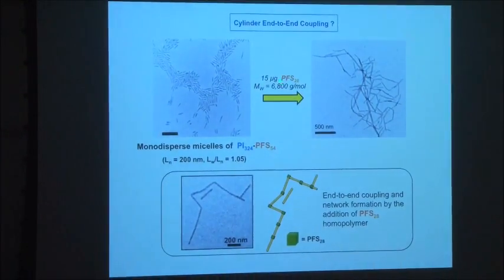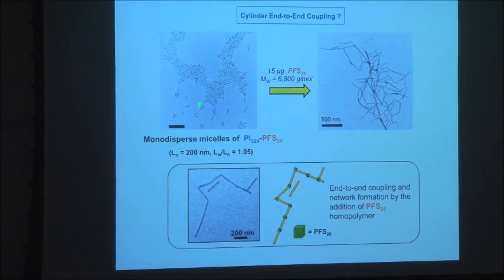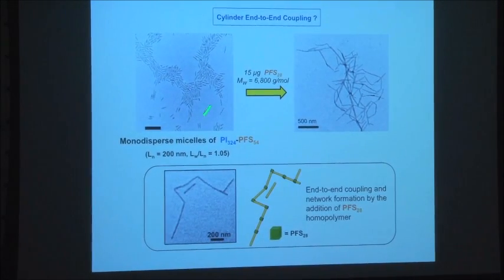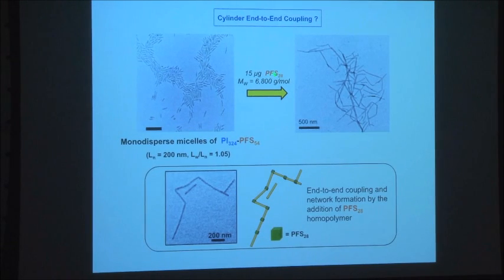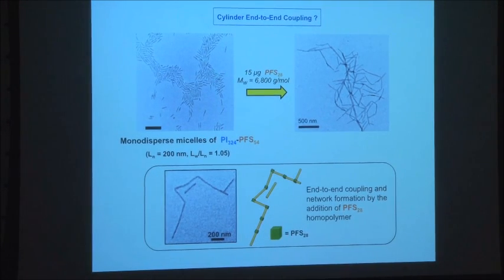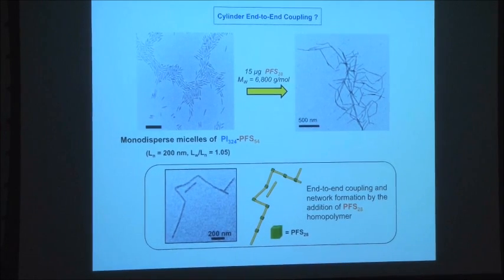And we have actually, hopefully I've got an example of that, which I can illustrate in here. Yeah, here we go. We've actually been able to join structures together, and the way you do it is you can add some homopolymer. If you take well-defined seeds, and these are, as far as we can tell, indefinitely stable, they don't join together. But if you add some homopolymer, this should add to the end, and then there's no steric stabilization, so you'd expect the structures to come together, and that's what you find.